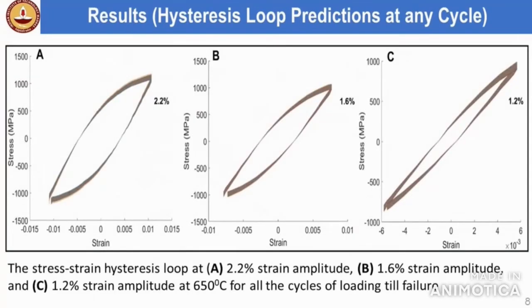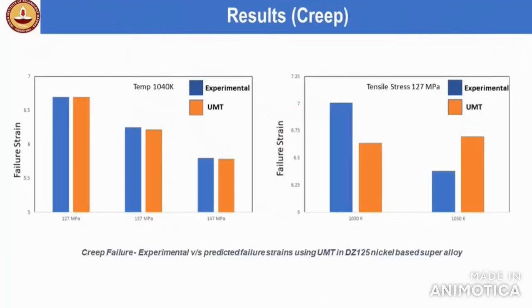Also, the loop prediction can be done at any strain amplitude and any number of cycles, which can be seen in this figure. Similarly, UMT is also being used to predict creep failure in nickel-based superalloys. Preliminary failure predictions obtained for DZ125 nickel-based superalloy show a small deviation from the corresponding experimental values. Below figures show the comparison of experimental and analytical results. Further investigation to model dissipation due to the dominant creep mechanism is now being carried out.